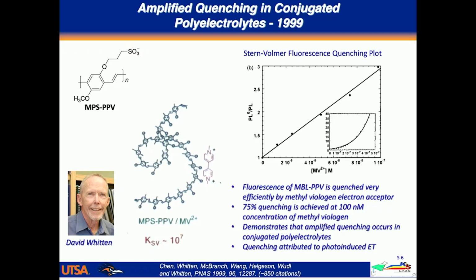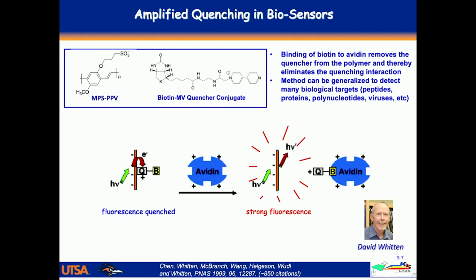This paper went a little bit further, and they showed how you could bring together this sensitivity imparted by the polymer and this quenching phenomenon and use it in a biosensor. What they did was a very simple scheme: they covalently linked the quencher, which is a viologen, to a biorecognition element, which is biotin. And when they add this conjugate to the polymer, its fluorescence is quenched. It takes just a very small amount because of Swager's amplified quenching concept.